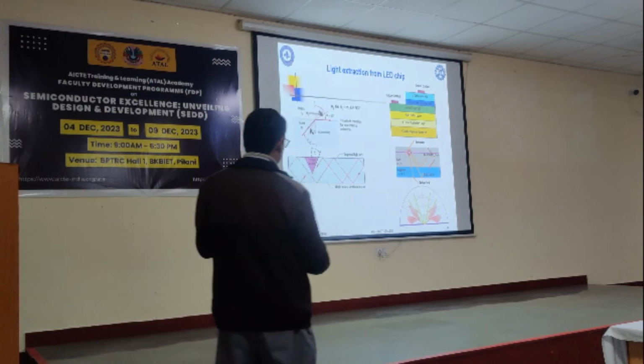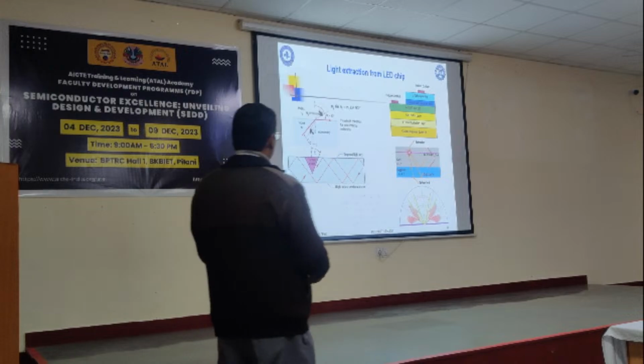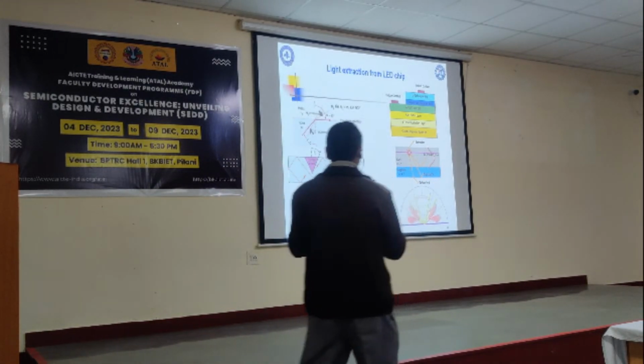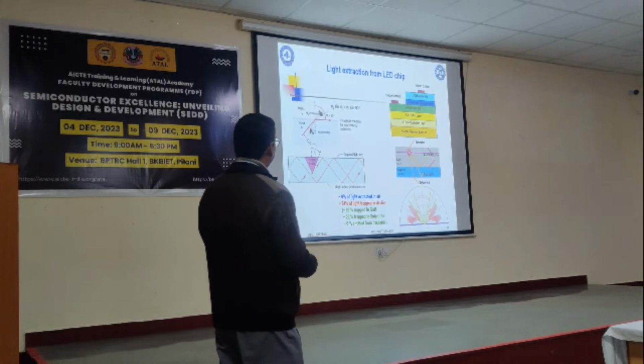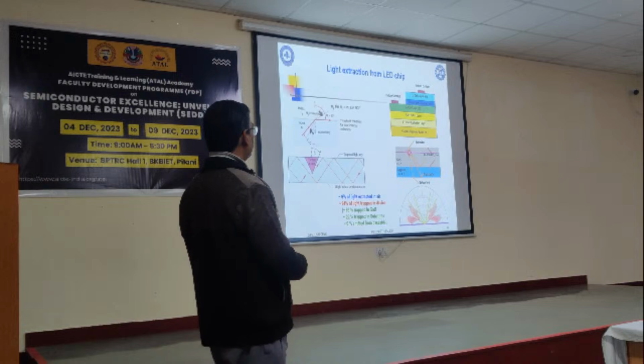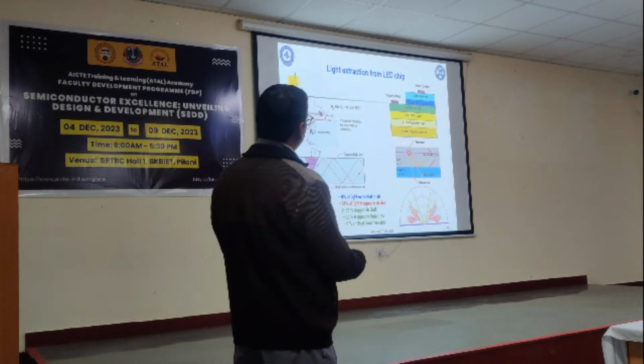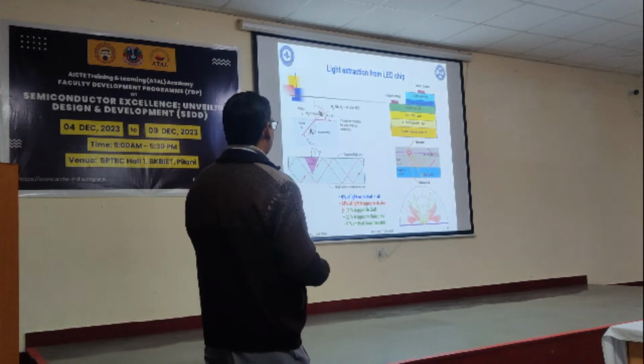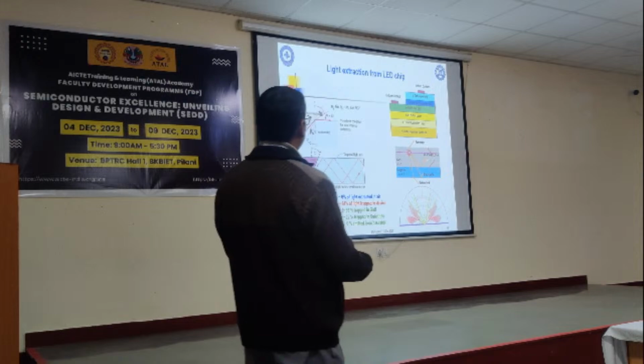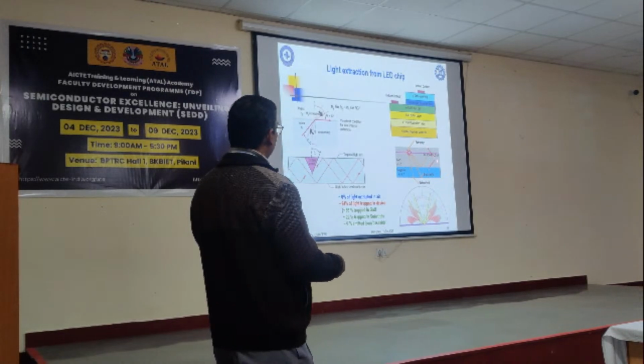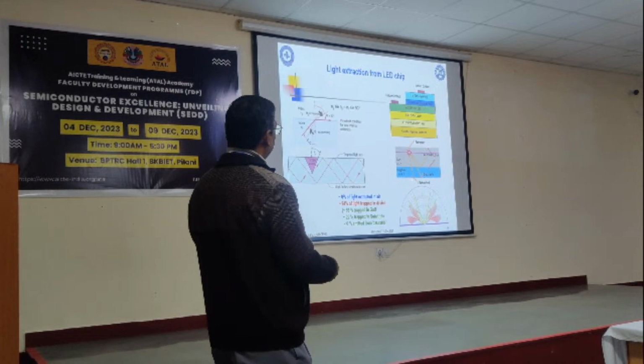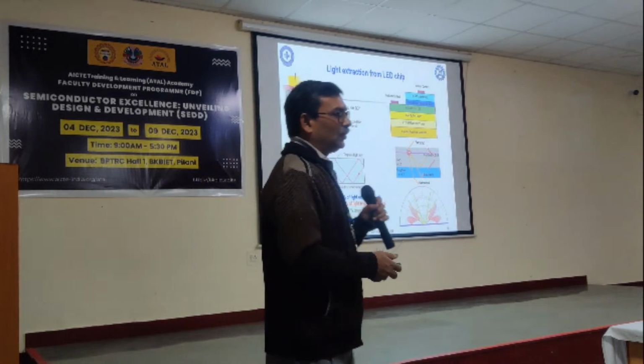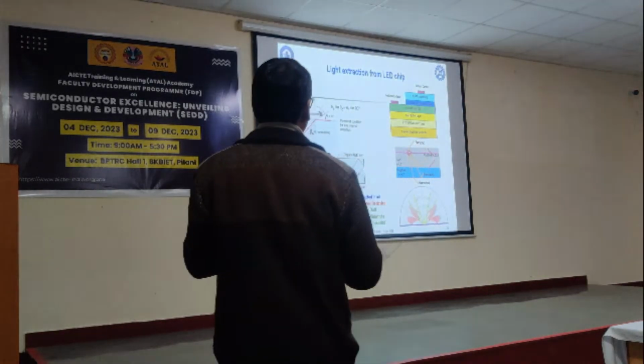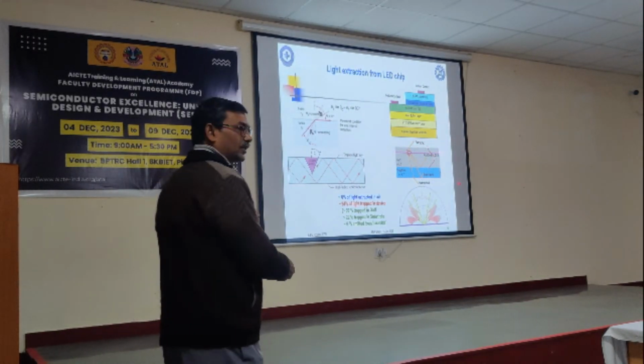So those are the refractive indices of gallium nitride and sapphire. If we check the values, of the light being generated here in the active region, around 6% is being extracted into the air, and the remaining 94% is trapped within the medium. The components: around 66% within the gallium nitride material, 22% within the sapphire substrate, and the rest 6% from that area. So how to maximize that portion and minimize this portion so that the light extraction increases much more?